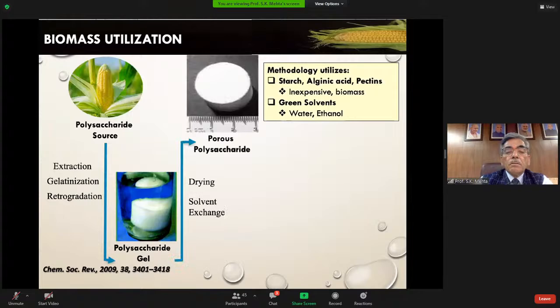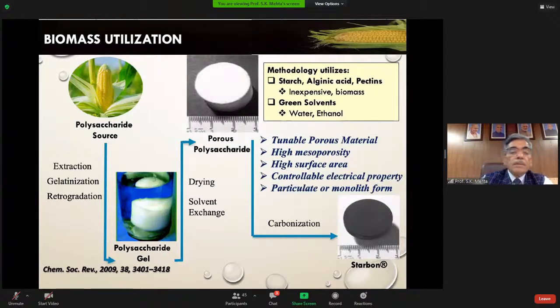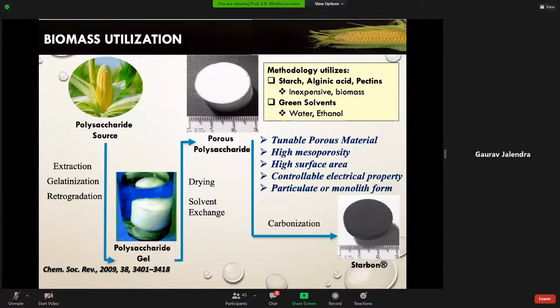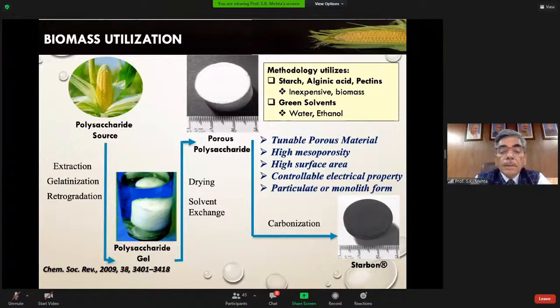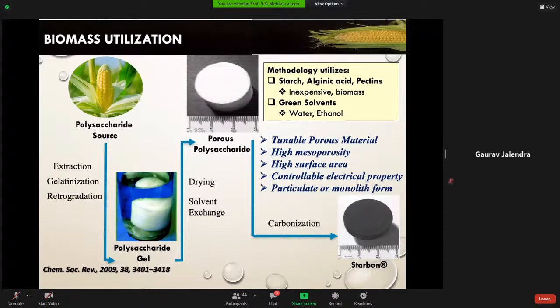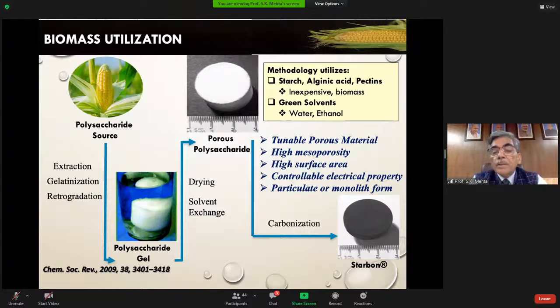Now, this is an overview which has been given, that we start with a polysaccharide source, and we do the process of extraction, gelatinization, retrogradation, and we get the polysaccharide gel. And this is all very nicely described in Chemical Society Reviews. Once we get the polysaccharide gel, after doing the process of drying and solvent exchange, we can get porous polysaccharides, and we can do the carbonization, and we get the product. And this product is a tunable porous material, with high mesoporosity, high surface area, controlled electrical property, in particulate or monolith form.